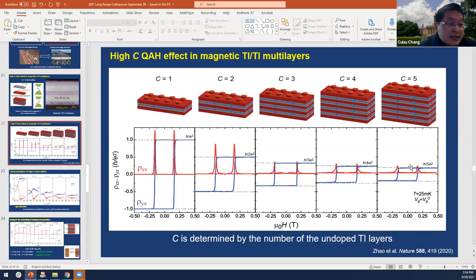We know that if C becomes larger, the Hall resistance becomes smaller. So now we can distinguish C equal to 4 and C equal to 5 quantum anomalous Hall insulator layers. But in my opinion, the longitudinal resistance becomes larger just because of synthesis. It becomes difficult to make the bulk insulating if you increase the thickness of the sample.